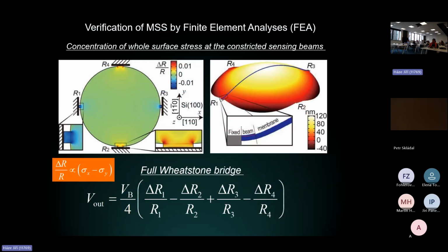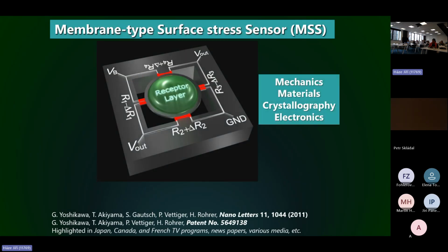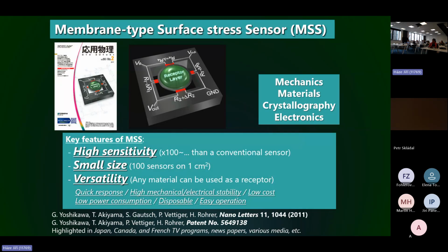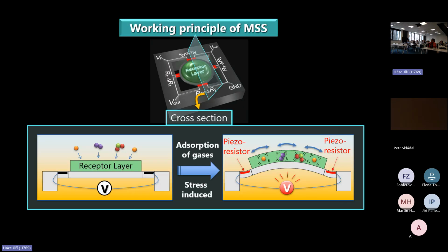And we also integrated the electrical features of this sensor. And then finally, this membrane-type surface stress sensor, in short MSS, was established. So with this structure, we have very high sensitivity and small size with MEMS process and versatility. It means we can use whatever materials as a sensing layer. And as you can see here, it works like this with a receptor layer coated on the thin silicon layer, and with absorption of gases, it mechanically swells and induces mechanical stress on the piezoresistors.